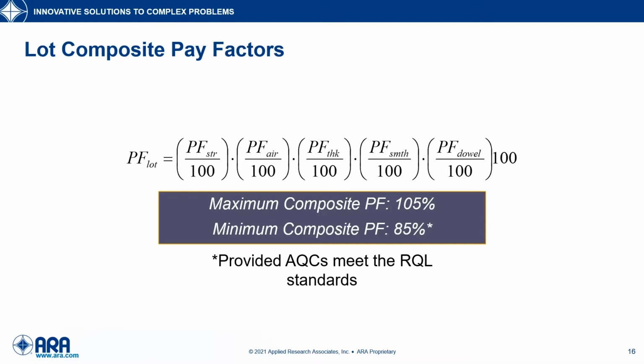And then just to wrap up on this performance construction spec, composite pay factor for the lot was calculated, and it used each of these individual pay factors, and they all had equal weight. And the Tollway selected a maximum incentive of 105% and maximum disincentive or minimum of 85%.